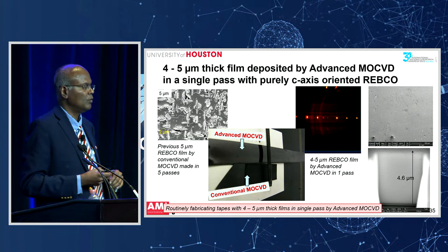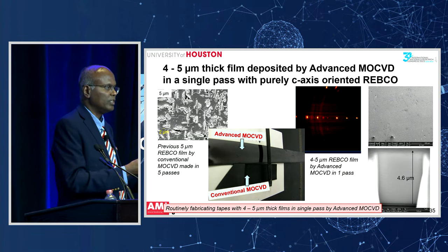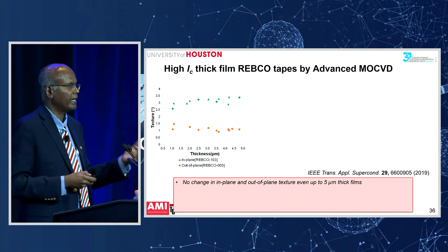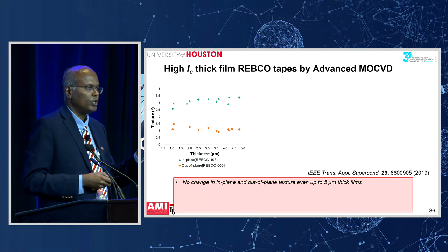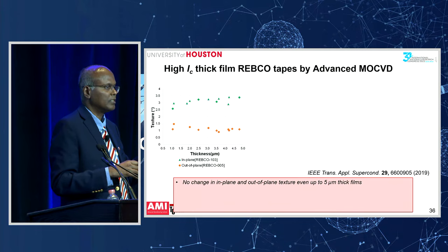So just by modifying, sometimes the solution is not necessarily in the process, but it's really in the engineering of the reactor or the equipment that's used to make the material. And you can see from this chart, remember I told you the texture is very important. You need to have the grain-to-grain misalignment within 5 degrees or so. It has to be in order to carry good current.